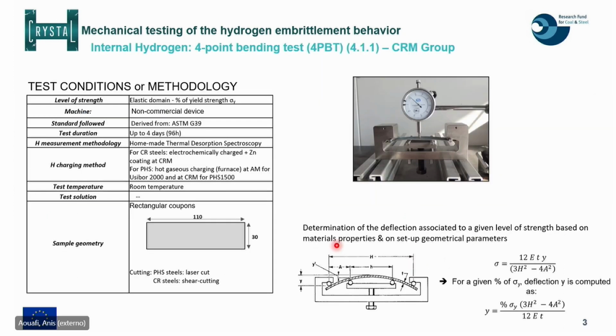Let me begin, first of all, with how we characterize the internal hydrogen using the 4-point bending test. The principle of this test is to impose a constant displacement using a screw here, and we measure the displacement using this comparator. This displacement is correlated, using a formula in the elastic domain, to the applied stress using the setup geometrical parameters, but also the material property like the thickness.